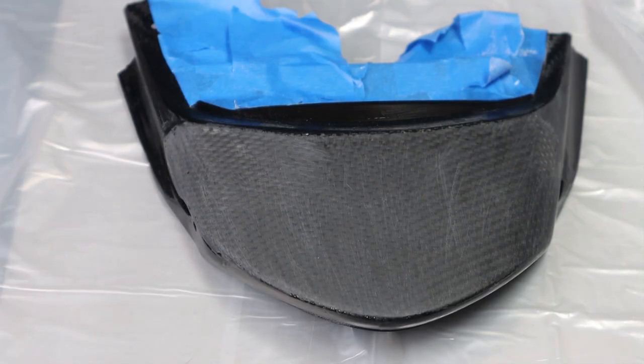We've shot 6 coats of clear, let it cure for 48 hours, and now we've sanded with 320 grit, and that has pretty much removed all of the pinholes. We had to do a lot of filling, and we sanded through those pinholes. Now it's looking pretty smooth, so what we're going to do now is shoot some more clear on top and see how this comes out, and that will determine whether we have to shoot some more clear or not, or we can just hit it with the Meguiar's Ultra Cut polishing compound, or Ultra Cut first and then polishing compound second, and see how it finishes up.